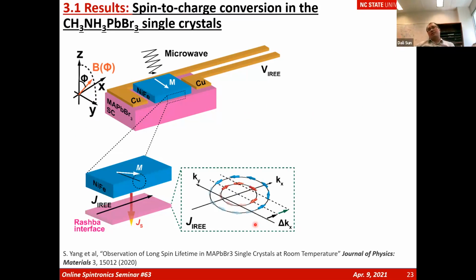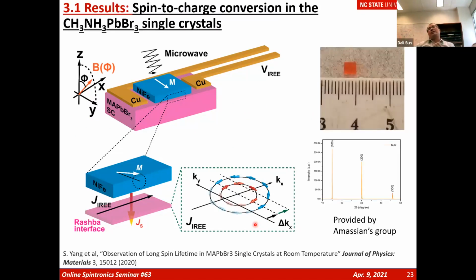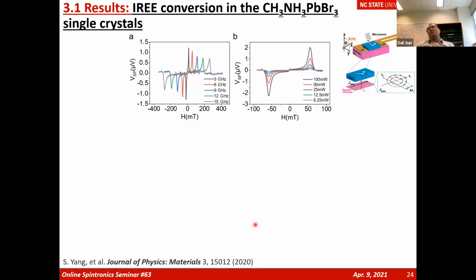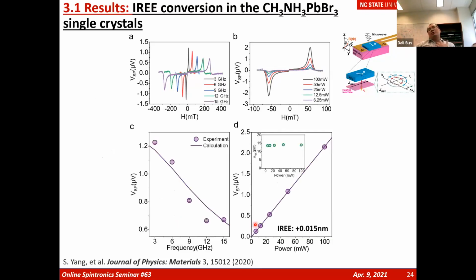to see what the efficiencies are. We fabricate the single crystals, provided by Amassian's group. We deposit nickel iron to measure the inverse spin responses in a single crystal. We measured the frequency dependence and power dependence. We clearly observe IREE responses, which can contribute to the spin-to-charge conversion